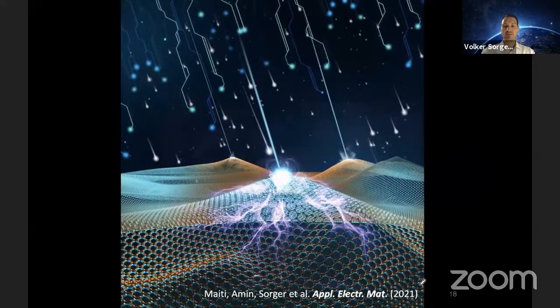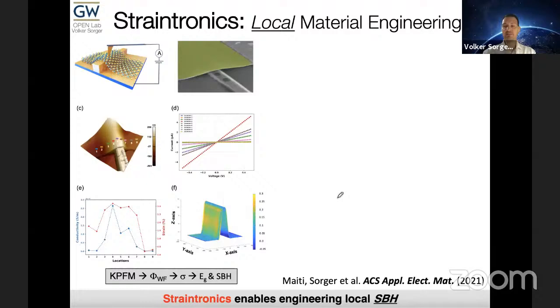Now we went on and performed an experiment where we strained this material even further and did IV tests. Here we put an AFM tip and mapped these IV curves locally. We did a local mapping. And we find indeed, if you look here, the conductivity as a function of location really dramatically shifts. You notice here the waveguide is roughly about here. This is the structure of this waveguide. At the edges, the strain is higher and is lower on the sides.